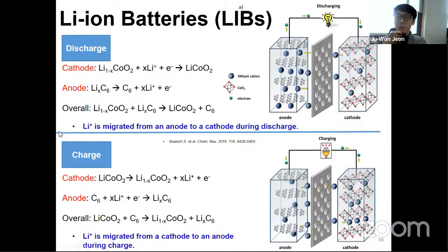These are the general chemical reactions for the lithium cobalt oxide based lithium-ion battery. For the discharge process, lithium cobalt oxide obtains lithium ions and electrons and converts to lithium cobalt oxide. Actually, the intercalation reaction takes place in the cathode. At the anode side, the graphite loses electrons and lithium ions at the same time. The electrons from the graphite anode are transported to the cathode, and the lithium ions are transported through the electrolyte and intercalated into the cathode during the discharge process.